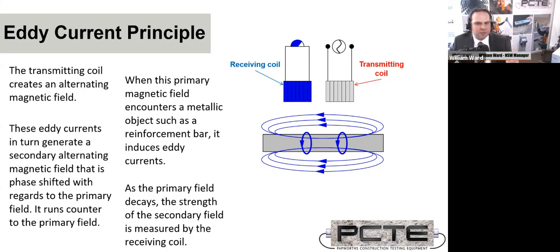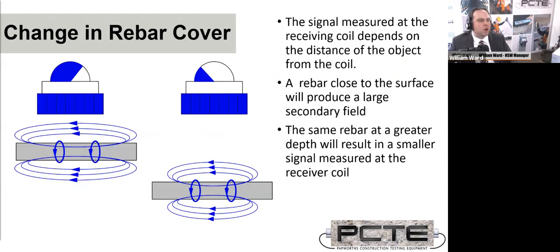One other key point of interference with this kind of measurement is if you have a welded mesh, it will cause more signal to return than conventionally constructed rebar layouts where it has been tied together. So if your measurements seem to be out from what you expect, and it's something like a slab on ground where the reinforcing is really only there for crack control, it might be that you've got a welded mesh, which will really throw out diameter estimates and will have an effect on your thickness measurements as well. Now, the welded mesh is going to reduce depth on the cover. It's not going to increase it, the additional electromagnetic signal.